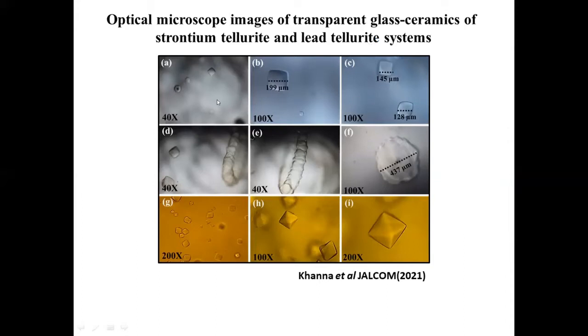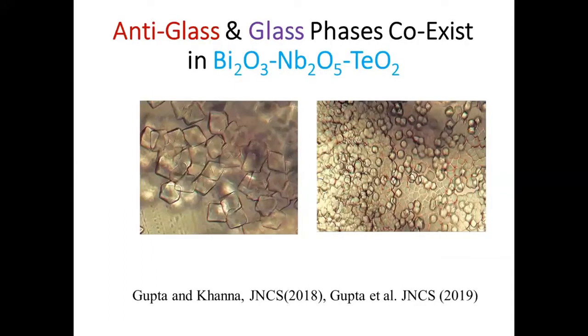And we see mostly a smooth background, but in some regions, we see these crystal-like things. Some inclusions are there, and these inclusions have a definite morphology also. You can see this in this last photograph, and these are pictures taken under an optical microscope. And these inclusions are not crystals, but disordered crystals, which are known as anti-glass phases. Similar effect we have found in bismuth niobium telluride system. Again, you see inclusions in a glass matrix. Two different phases are existing simultaneously in your system.